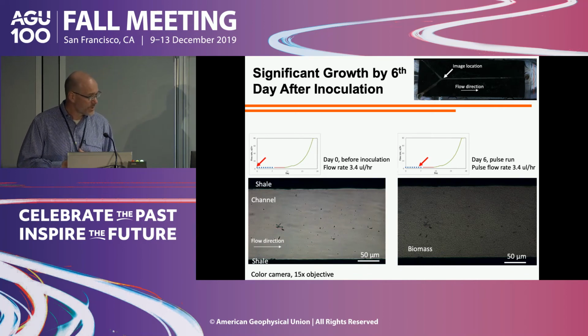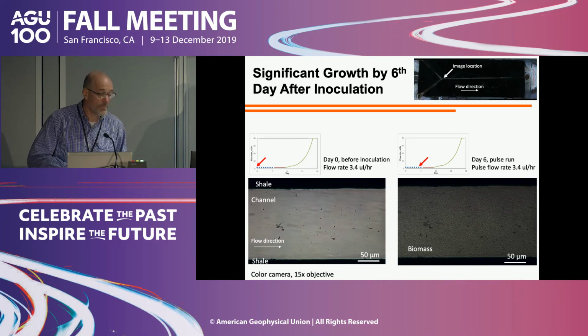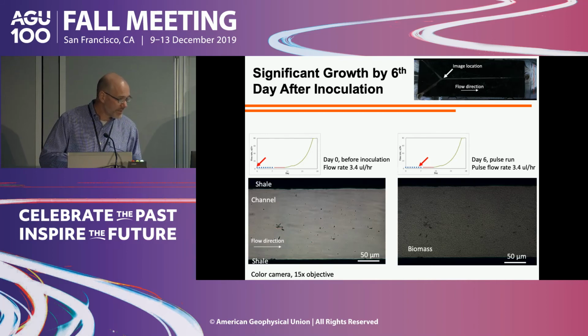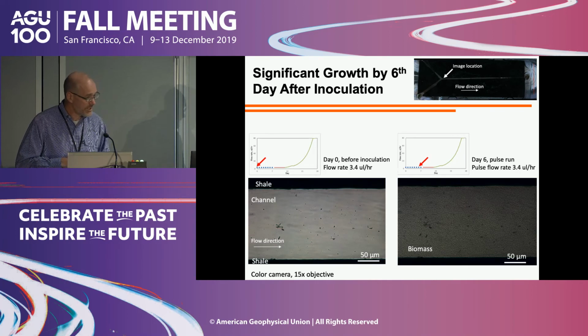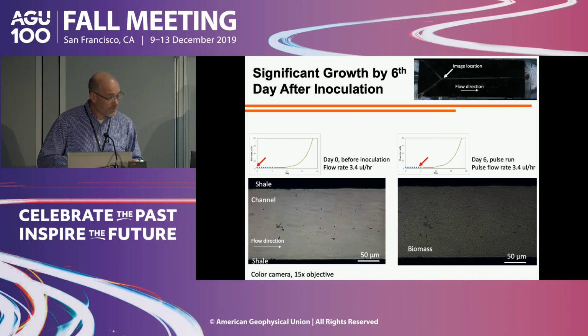So here are the results. This is basically 0 and 6 days, and I'll show you a sequence of time images here. At 0 days, there's really nothing in the reactor yet. And at 6 days, they've had this stop, start. When the organisms don't have continuous shear or continuous flow, they tend to be planktonic, meaning they aren't really forming a biofilm yet. Some of them are. They start to stick, but you don't really see that classic biofilm shape. But what we do see is a lot of little individual organisms, and it's hard to see. You see kind of stipples, but I'll show you some better images in just a little bit. As time goes on, you start to see the biomass growing in that channel. That's just a piece of the channel near the inlet where these things are reacting.